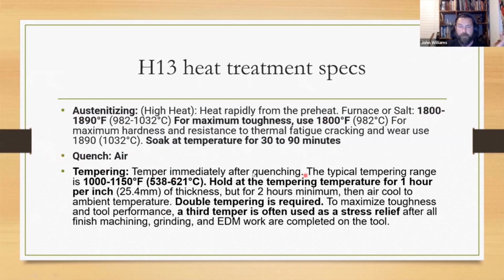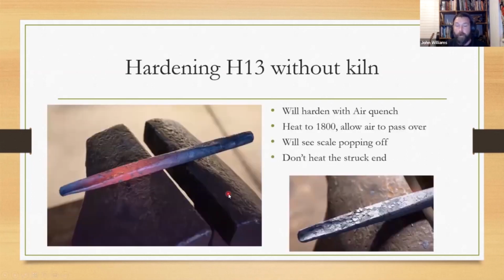And tempering, this is another thing that I want to point out, is that technically you should be tempering at 1000 to 1150 and hold for an hour per inch. Well, you're not going to do that in the oven that you bake cookies in, right? Hardening H13 without a kiln. Now I have a kiln, so I can anneal this. So I have a struck end because I can do that, but you don't want to ever heat this whole area up. And what are the particulars here? It's going to harden in air, and you need to heat it to 1800.